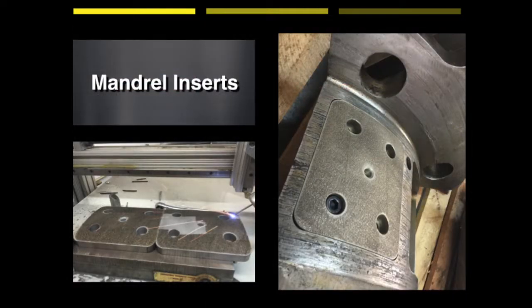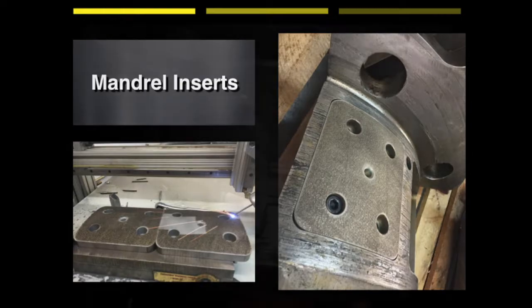Our initial fix for this problem was to simply coat the OD of the stub mandrel with a coarse grit ESD coating. This helped a great deal, but because of the very high loads, the coating still failed within a couple of months. It's important to remember that because ESD creates an alloy of the electrode material and the substrate, it matters what the substrate is. The solution to our mandrel problem was to create a set of custom inserts made from hardened A2 tool steel to which we could apply our coating.